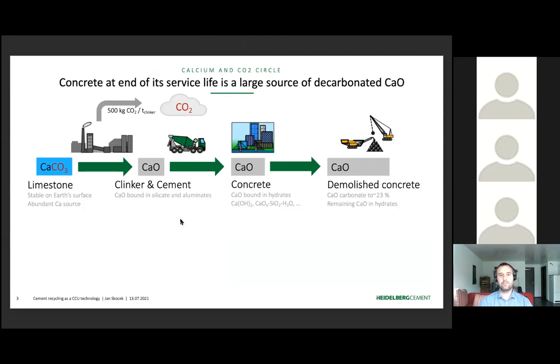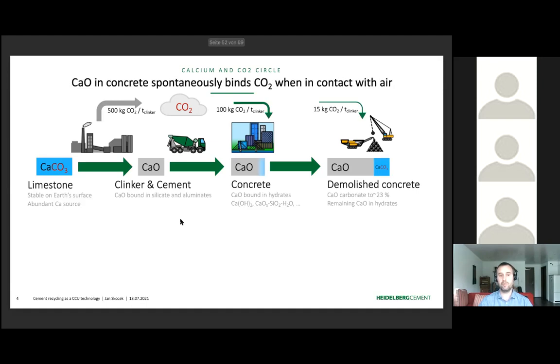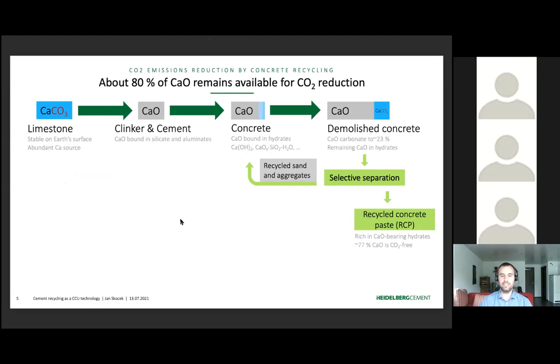But contrary to other products, we have one big advantage, and that is that the main product of clinker production, the calcium oxide, doesn't disappear. It stays in the concrete for the entire service life and even during the demolition. It carbonates naturally, so it binds some of the CO2 back, as calcium carbonate is the stable form of calcium oxide. But still, even after decades of service life, most of the calcium oxide provided via cement to the concrete is still there as a non-carbonated material. And in our project, we are trying to recover this calcium oxide and recycle it back to the production of clinker, cement, and concrete.